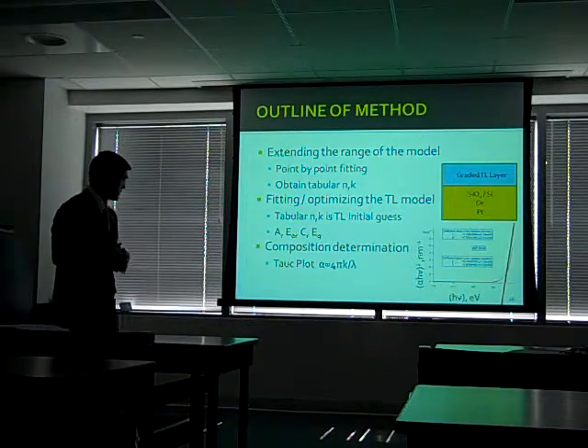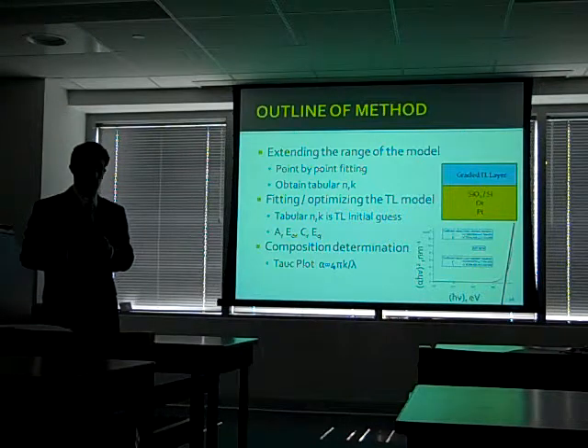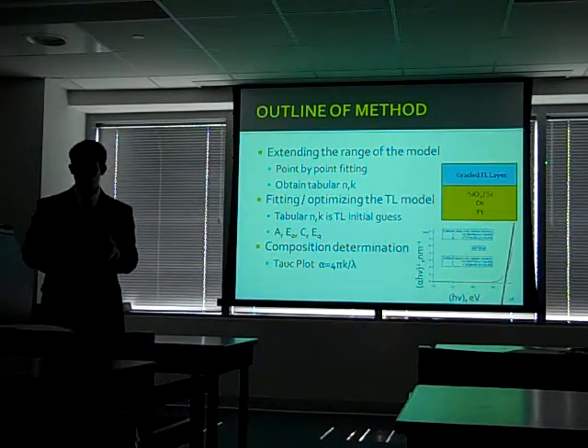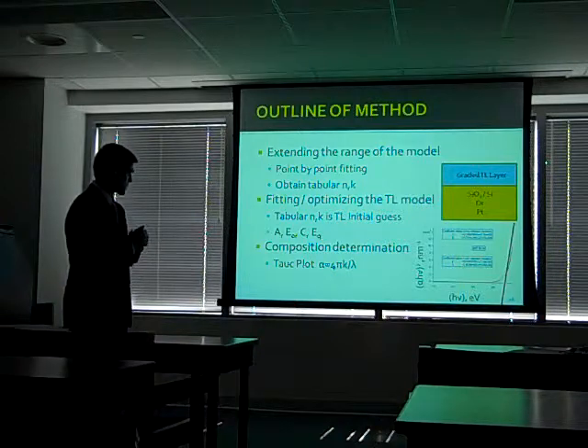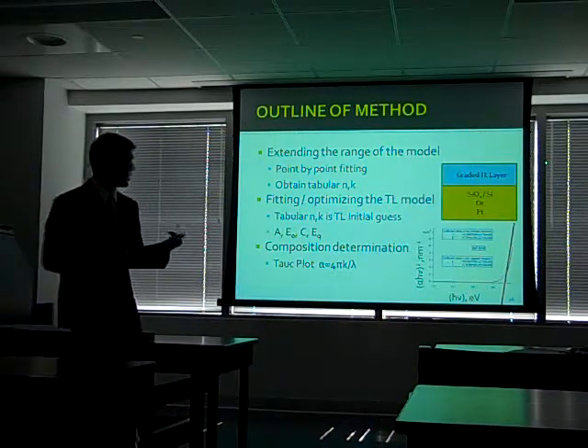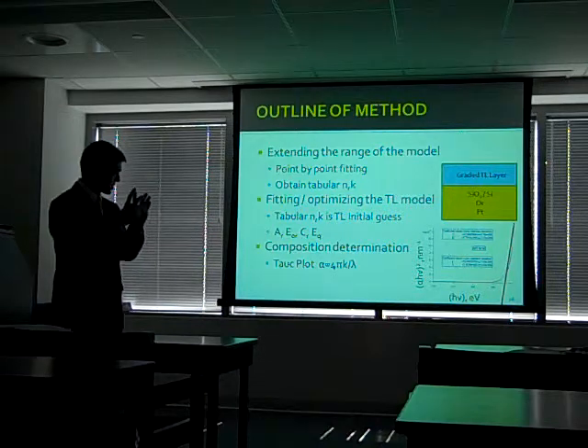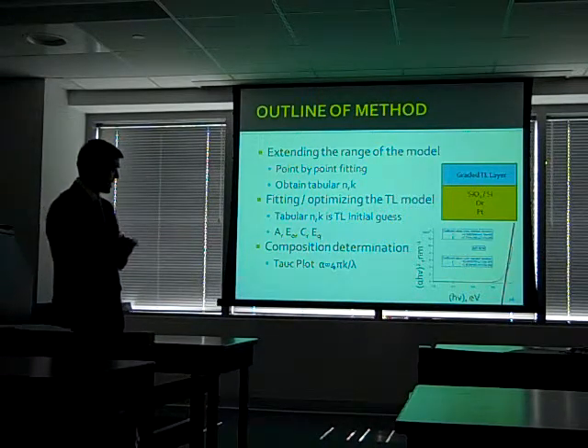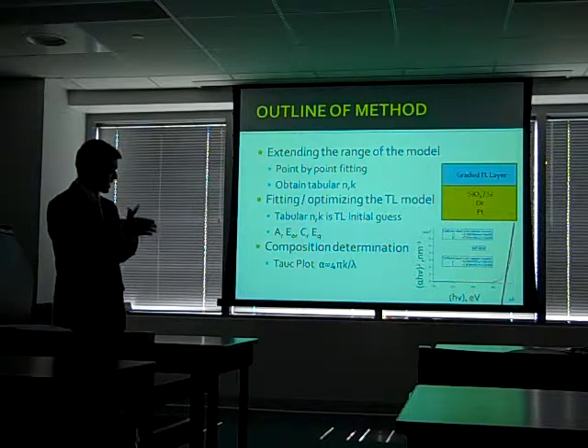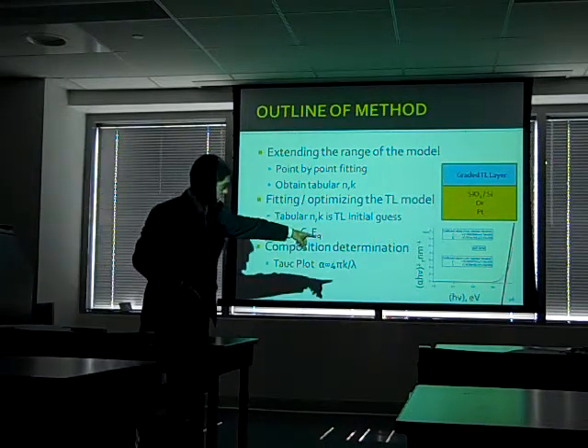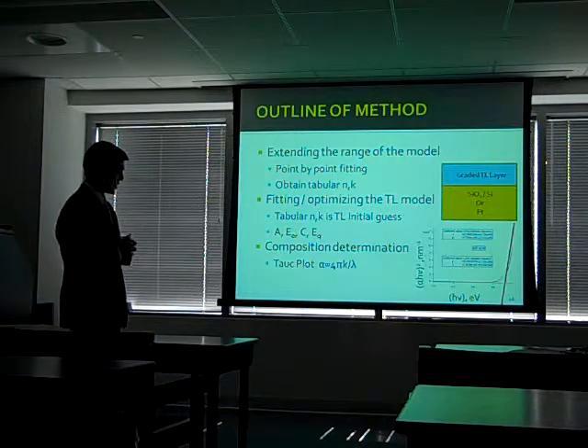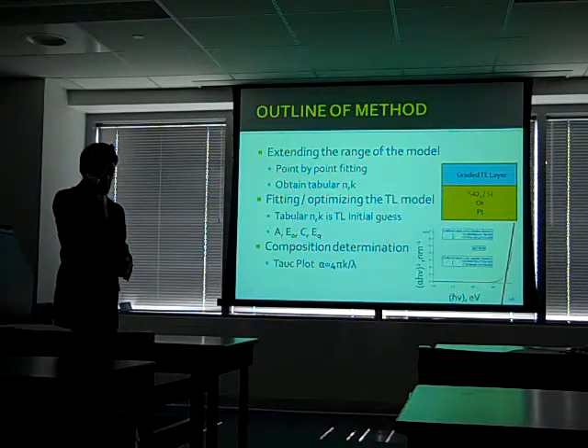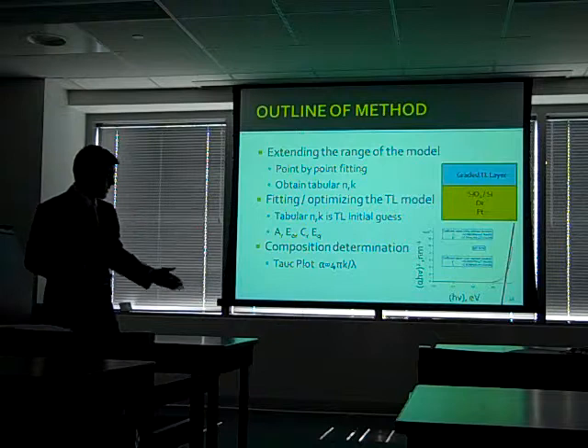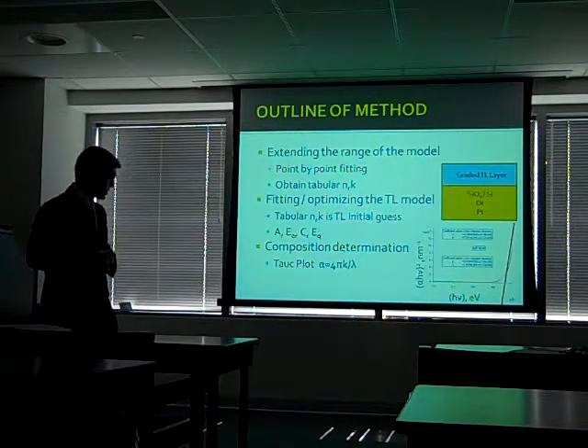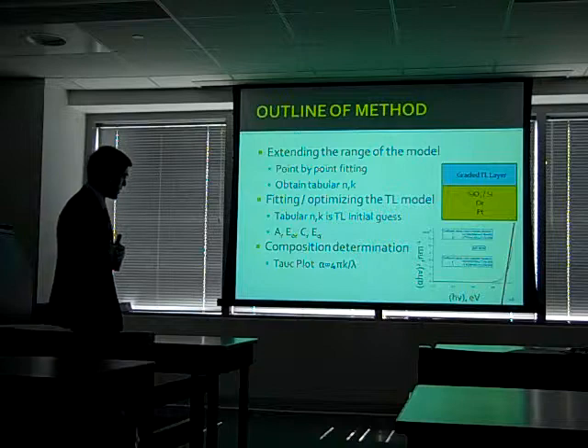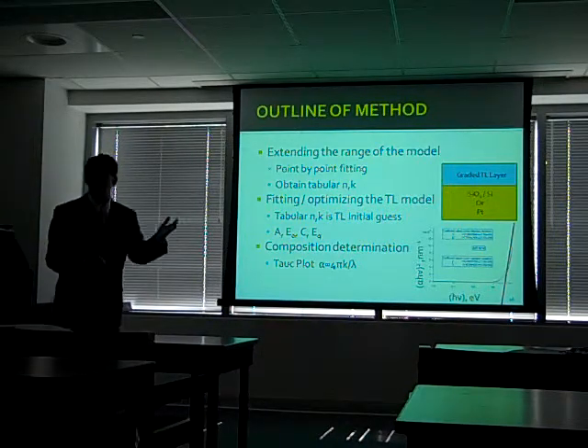And now to get composition, we'll take the extinction coefficient, K, and use it to construct a Tauc plot. The Tauc plot goes by first calculating the absorption coefficient, alpha, as 4 pi times the extinction coefficient over wavelength. And then you plot alpha times energy squared, as this graph on the bottom shows you, as a function of energy. And then extrapolate the linear region of the curve. Now where that line crosses the x-axis corresponds to the band gap energy. So again, this is the Tauc plot, and this is how we extrapolate the band gap based on the optical constants.